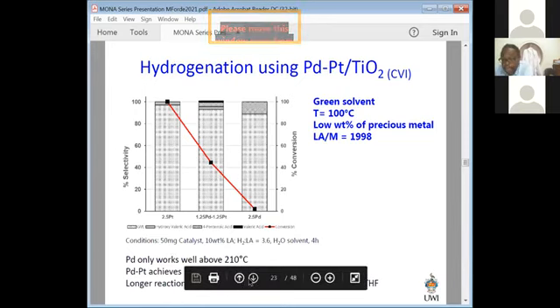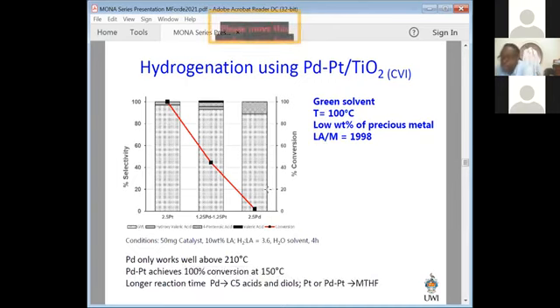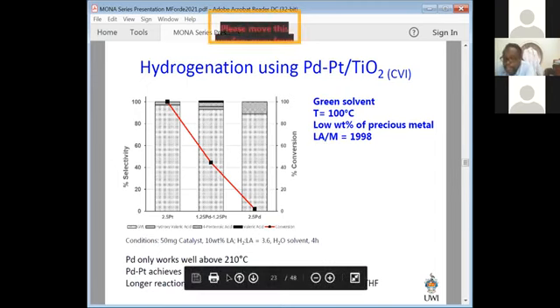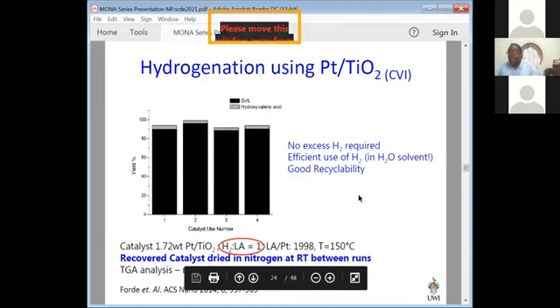If we leave this for longer, we see that we get further products, which means, of course, this reaction is only 4 hours. Typically, these sorts of reactions use 8 to 16 hours for materials which are very difficult to convert. And so we can actually get fuel blenders, we can get materials for use as solvents or in other synthesis reactions in this way. So this was published. That's fine. And so we went on to see what else we could do with it.